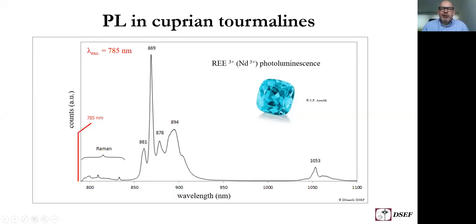And the stones, both the unheated and the heated stones, however, showed a very strong photoluminescence when you illuminate them with a 785 nanometer laser. So this spectrum is taken with Raman spectroscopy, and you can see here these bands, which are a result of rare earth concentrations, particularly neodymium. Now, we were interested in why both stones, unheated and heated, show rare earth luminescence, but did not show the luminescence under UV light.